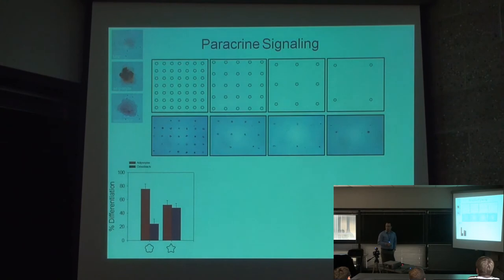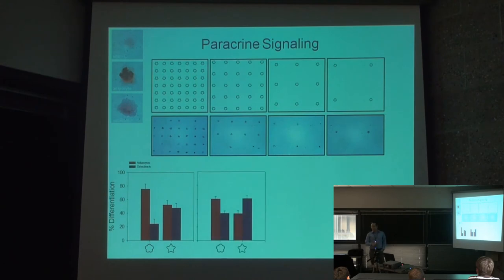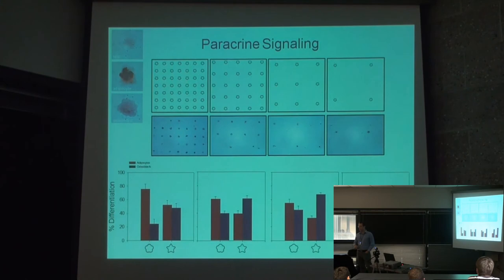And something really startling came out of this, where at very high density, we see most of the cells are turning into fat. But as we increase the spacing between them, we see an enrichment in cells that are differentiating to bone. And my jaw absolutely dropped on this because it was unexpected. We see at high density a lot of fat, but as you decrease the density, you get almost a complete switch here, where now most of your cells that are very far spaced apart are expressing bone cell markers. So clearly something's going on here.